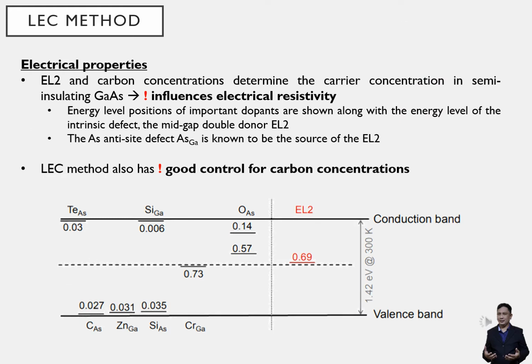EL2 and carbon concentrations determine the carrier concentration in semi-insulating gallium arsenide and thus influence electrical resistivity. Shown here are the energy level positions of important dopants along with the energy level of the intrinsic defect, that is the mid-gap double donor EL2. Also, the arsenic anti-site defect is known to be the source of EL2. The LEC method also has good control of carbon concentration, which is important for the semi-insulating property.